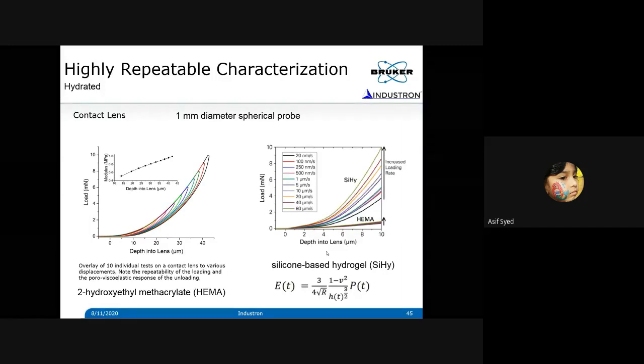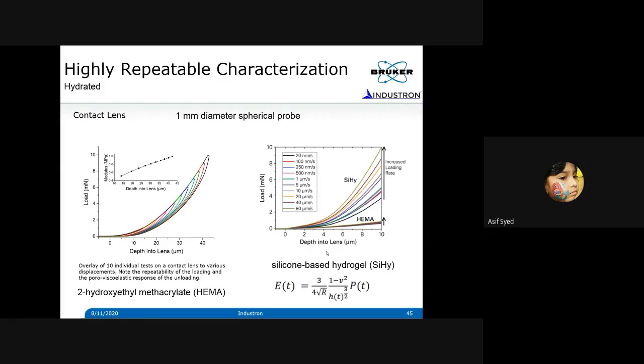The one thing that I want to point out is all these experiments were done in a hydrated condition, which means it's submerged in a buffer solution. So when you do that, you don't have much of an adhesion problem. This is one trick people use. When you have a probe making contact on soft materials like this in dry condition, you have this problem of adhesion between the tip and the sample. Most of the time you have to test in a hydrated condition anyway, but when you do it in a submerged condition, you can minimize this adhesion. That's why you can see in this load displacement curve there is no attraction, jumping in and jumping out, or any of those characteristics. I'll show that type of curve real soon. So you can readily use Hertzian contact mechanics here and measure the modulus as a function of depth.